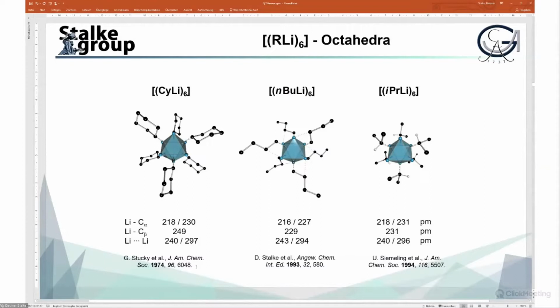The first who discovered that was Galen Stucky in 1974, when he determined the structure of cyclohexyl lithium. What you can see is an octahedron of lithium atoms with 8 faces. 6 of them are bridged by the deprotonated carbon atom, and 2 of them at opposite sides of the octahedron remain unoccupied. This is the principal building block in n-butyllithium, the industrially most interesting starting material, with the same pattern.